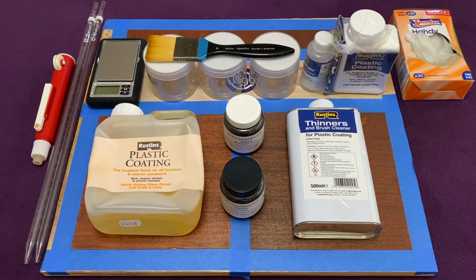So taking these constraints and information into consideration, I decided not to risk applying multiple coatings in a few hours, and instead conservatively chose to apply 1 coat at a time and let it fully harden at a temperature between 20 and 25 degrees Celsius for a minimum of 3 to 4 days. The only issue I experienced during that process were small blemishes resulting from trapped air bubbles in the hardened coating.